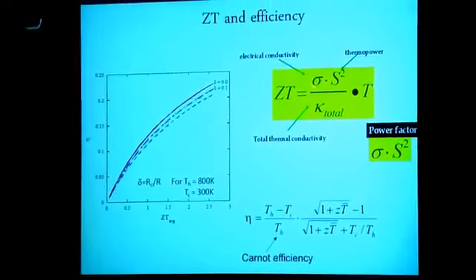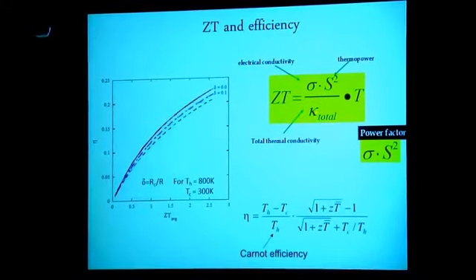So you see here you need high conductivity, high thermopower, and very low thermal conductivity. And the reason you want low thermal conductivity is you want to maintain that delta T. If the thermal conductivity is high, you're going to equilibrate, and you're not going to be able to use it. So you need very low thermal conductivity. And this is how the ZT relates to efficiency. So there's no upper limit to the ZT. Basically, the ZT defines the fraction of the Carnot fraction that can be used. So this is limited by thermodynamics, as it should be.